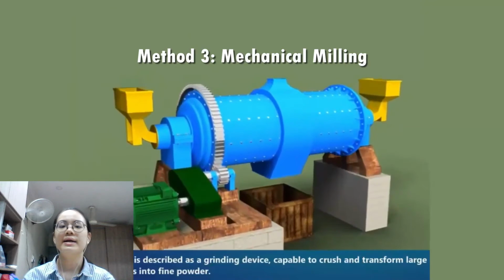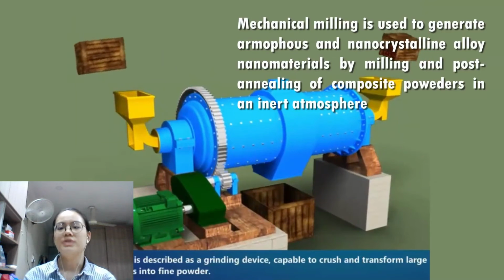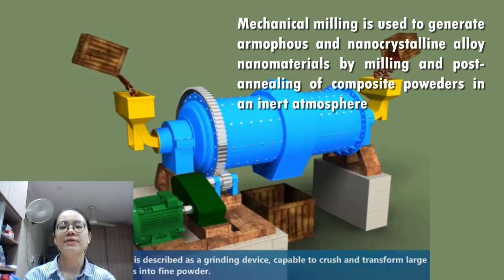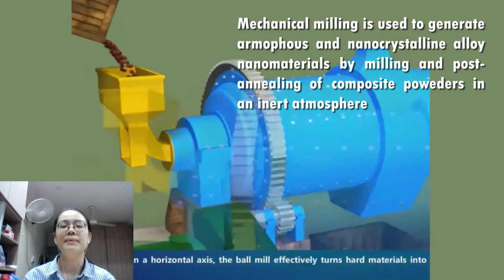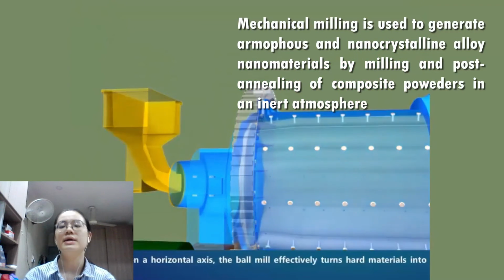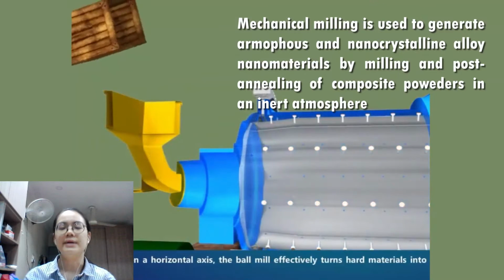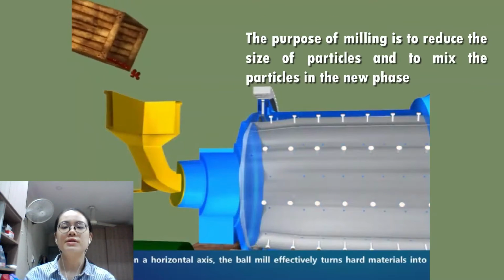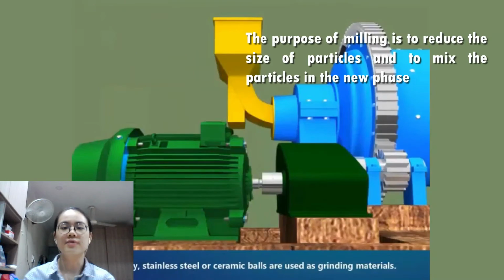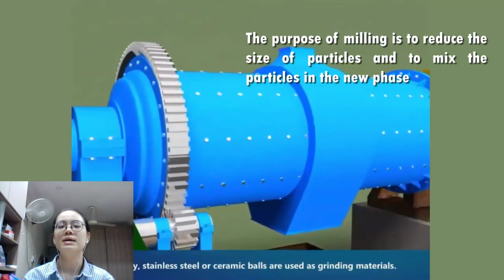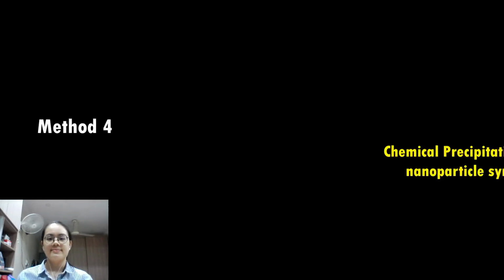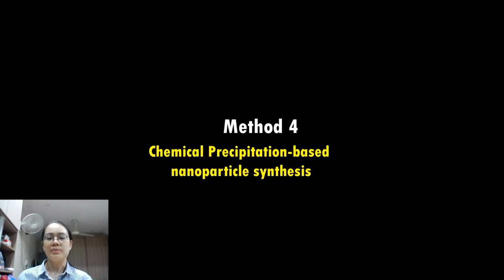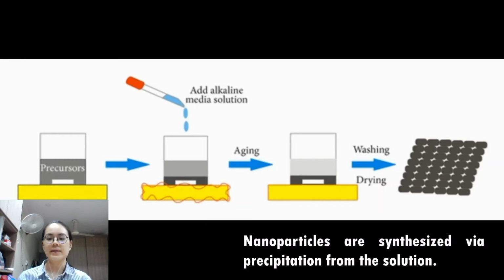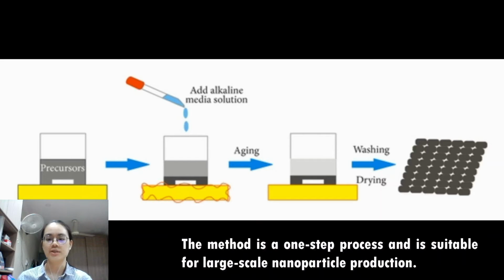Mechanical milling is used to generate amorphous and nanocrystalline alloy nanomaterials by milling and post-annealing of the composite powders in the atmosphere. The purpose of the milling is to reduce the size of the particles and to mix the particles into the new phase. The fourth method is chemical precipitation-based nanoparticle synthesis, and the nanoparticles are synthesized via precipitation from the solution. The method is a one-step process and is suitable for large-scale nanoparticle production.